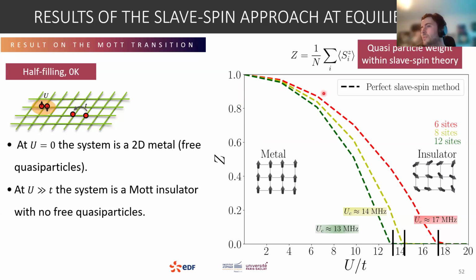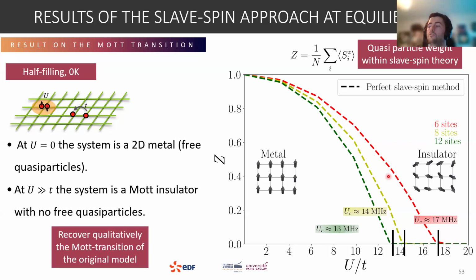And here it's a perfect simulation without atoms, without anything, just a perfect simulation of the spin method to show you that we can recover a phase transition. Of course, the transition value depends on the number of sites we are taking into account. But when U over T is small, Z is not equal to 0, and then we have quasi-particles. And when U over T is larger than a certain value, Z equals 0, and the system is frozen. We are in the Mott phase. So with this method, we can recover qualitatively the Mott transition of the original model. It's quite the same result that has been found by people using the spin method.